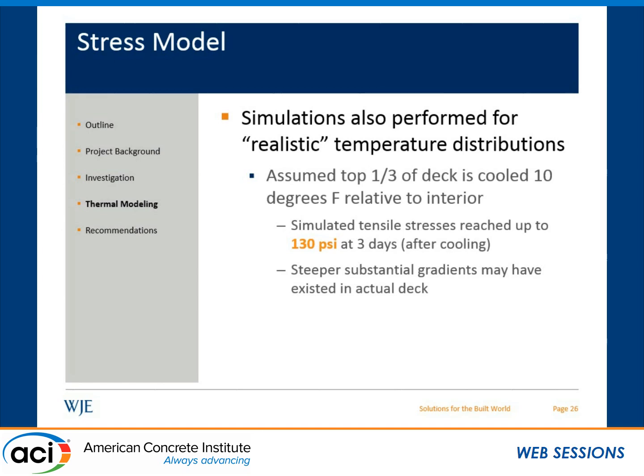What we simulated first was that the top third of the deck was cooled 10 degrees cooler than the interior of the deck. And what the simulation showed was that we were generating tensile stresses up to 130 psi after just 3 days. Just as a comparison, the tensile strength of the concrete at this age could be about 300, 350 psi. So just this 10 degree difference at the top surface of the deck is enough to cause about 50% of that tensile stress to be generated. But we can also see steeper gradients may have existed in the actual bridge deck, which may have substantially increased those stresses.